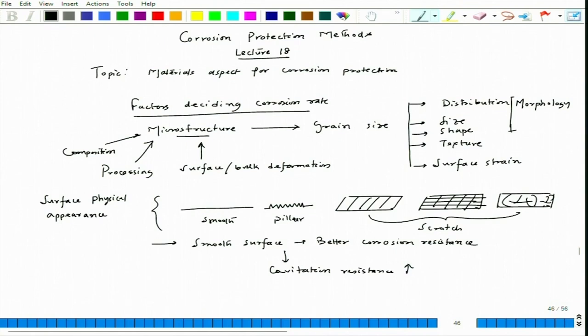Because if it is smooth, definitely there will be difficulty in nucleation of bubbles on top of it. And as we know, cavitation is nothing but formation of bubbles due to change in water pressure, and then collapse of those bubbles giving shock waves on the surface, and gradually corrosion goes on. But mainly, this evolution is formation of bubbles and then collapse of bubbles, leading to mechanical deformation on the surface, and that would also enhance the surface reactivity, and it would also increase the corrosion rate. So corrosion resistance improves if it is a smooth surface.